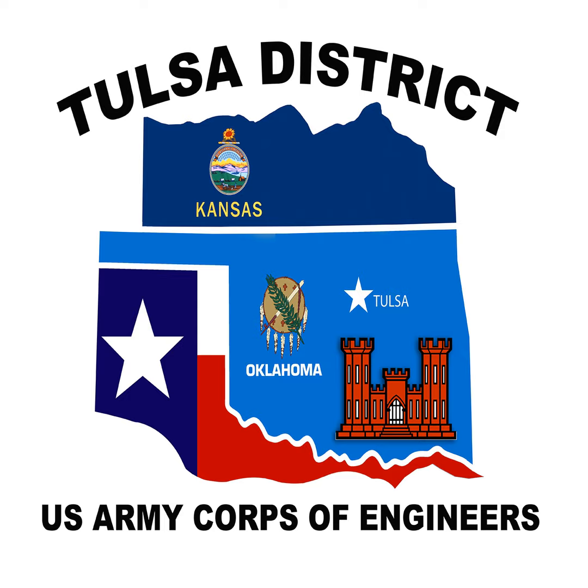Well, so for the test that we did, where we encapsulated the entire end with about 1.5 inch thick to 3 inch thick coating, you might call it. So it was a little bit more extensive than a patch, but we actually saw a 40% increase in the strength compared to what the original beam could do, which surprised all of us a little bit, but was a very exciting finding. Oh, wow.